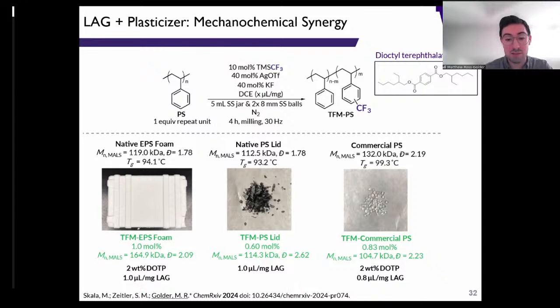All right, so we can take the same native foam. We get about 1 mole percent tagging in the presence of the 2 weight percent DOTP. So a really small amount of plasticizer being added in, and we retain really nice control over molar mass. The coffee cup lid worked pretty well as is, so we didn't touch those conditions at all. Same with the commercial polystyrene, just a small change in molar mass in the presence of our DOTP.